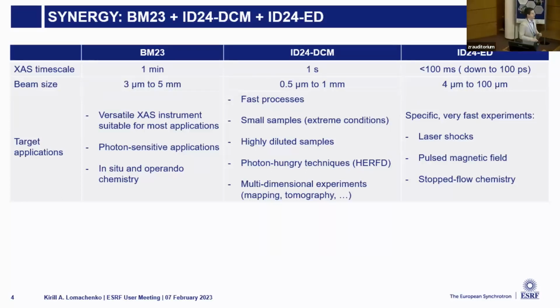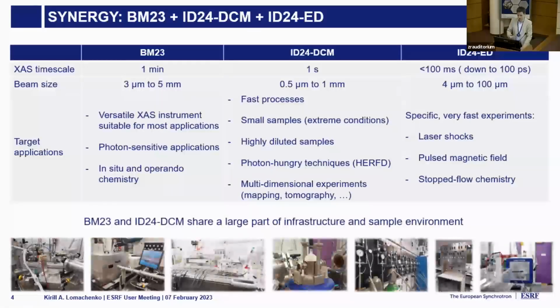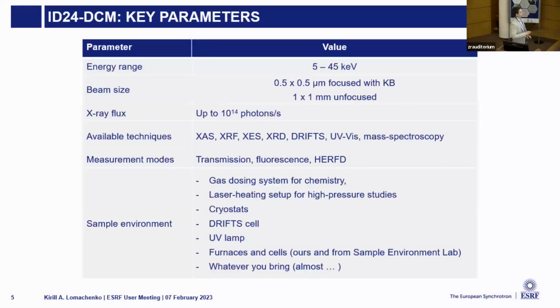ID24 energy dispersive is the beamline that Rafaela Torchio presented last year. It's a completely different way of measuring EXAFS, using a polychromator instead of a monochromator, in a single shot, which allows a very high time resolution down to hundreds of picoseconds, and it's dedicated to very specific experiments like laser shocks, pulsed magnetic field and stopped-flow chemistry. And the good point also is that BM23 and ID24 DCM share a lot of infrastructure and sample environments. So we are quite complementary.